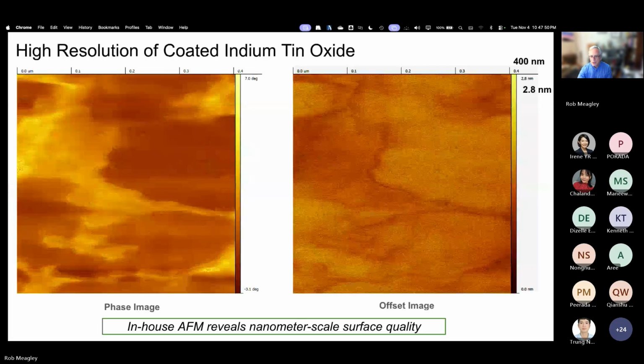And along with resolution, you can also look at distinctly different chemical environments. This is an indium tin oxide surface that has relatively flat topography, at least at this scale. We're looking at a 400 nanometer by 400 nanometer field size. On the right, we have offset. That's just the topography, more or less the kind of imaging we've been looking at mostly so far. And on the left, we have a phase image.